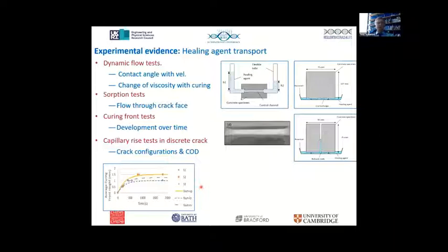Thamish has done quite a lot of work, and Diane, various people working with Diane have done quite a lot on this. When the healing agents move through the crack, if it's low viscosity, the dynamic motion can change what happens at the meniscus. We had to study that. During the course of healing, viscosity can have quite an effect. Viscosity changes due to curing can have quite a change in the flow property.